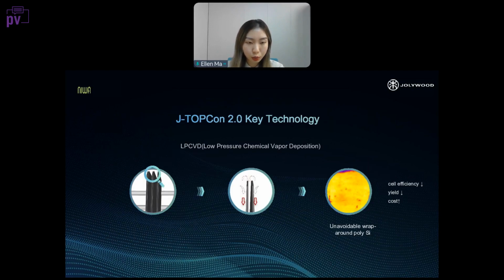And here is the process to introduce why the LPCVD will need to have the additional cleaning process. The LPCVD is called low pressure chemical vapor deposition. When the temperature is very high, the silicon wafer will become softer. So the gas will be diffused inside in the middle of the wafer, which will cause some unavoidable wrap-around of the polysilicon. And if we look at the EL picture here, we can see there is a significant dark edge at the edge of the solar cells. As a result, it will reduce the cell's efficiency and will reduce the yields, and consequently will increase the cost.